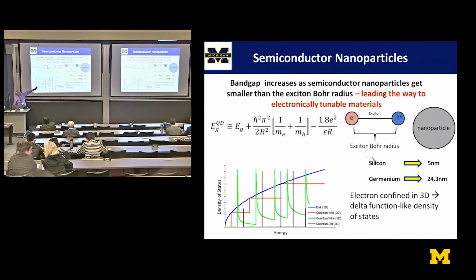We've heard a lot about the unique properties of semiconductor nanoparticles, which can also be produced by these lasers. In particular, one can modify the effective band gap of these materials by changing the diameter of the nanoparticle. One can increase the band gap by making the diameter or the radius smaller. And this suggests a way to electronically tune the semiconductor nature of the nanoparticle to match various requirements, for example, to match the peak in the solar spectrum if you're interested in using nanoparticles for energy harvesting.